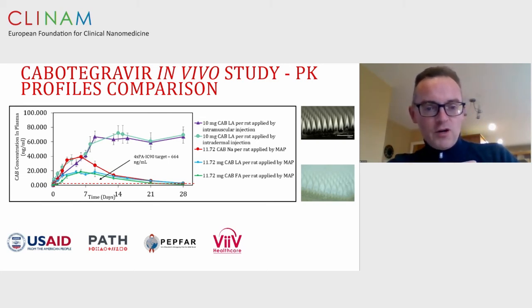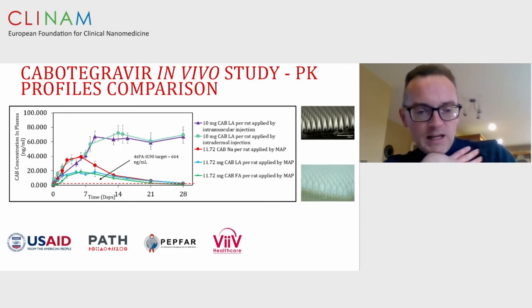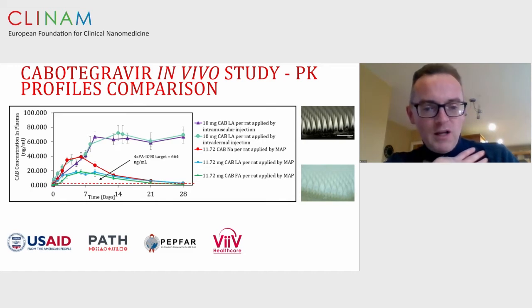And what we found was that after around 7 days, the free acid and the long-acting injection formulation put into microneedle form gave quite good levels, in that we were above 4 times the PA-IC90. And that was true right up to 28 days for both of those. But when we used the sodium salt at day 7, we were actually comparable to the intramuscular and intradermal injections that had similar amounts of drug. And thereafter, the plasma levels started to decay. And actually what we believe is happening here is that the microneedles obviously aren't delivering all of their drug.